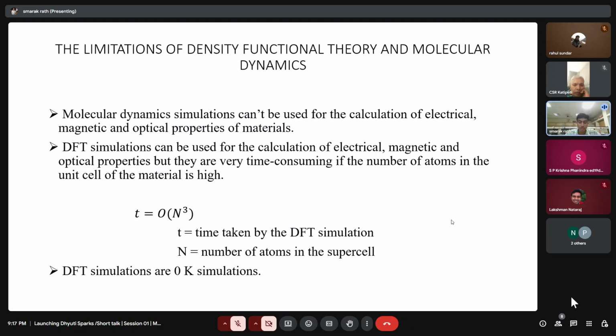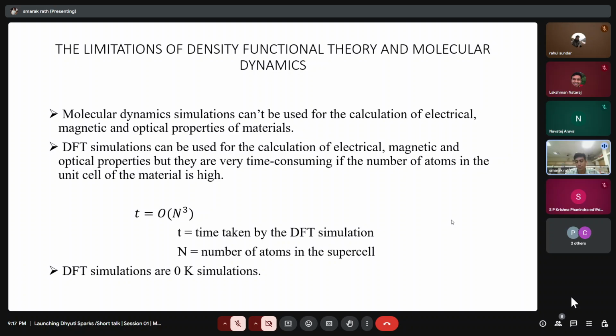And in addition to that, DFT simulations are essentially zero Kelvin simulations because DFT is based on an approximation called Born-Oppenheimer approximation, where we assume that all the nuclei of all the atoms are frozen, absolutely frozen, which means that these are zero Kelvin simulations because at any temperature above zero Kelvin, the nuclei are going to vibrate. So that is another limitation of DFT around which we have to work. And so you can clearly see that there are limitations in both DFT and molecular dynamics.